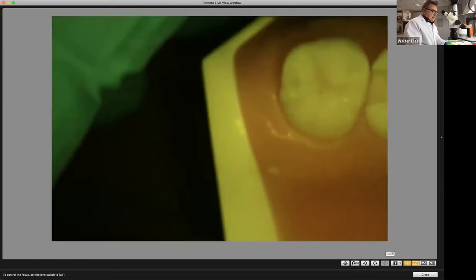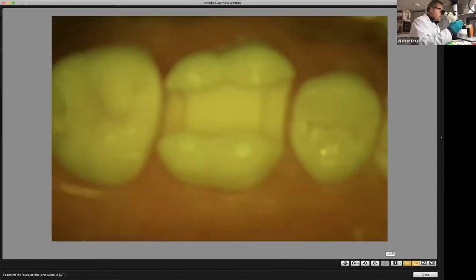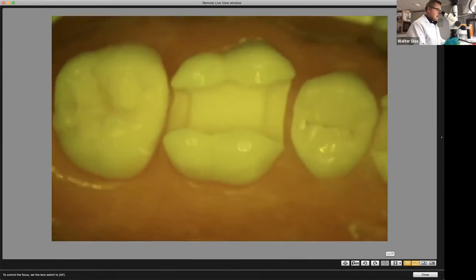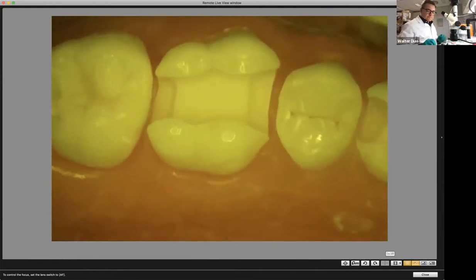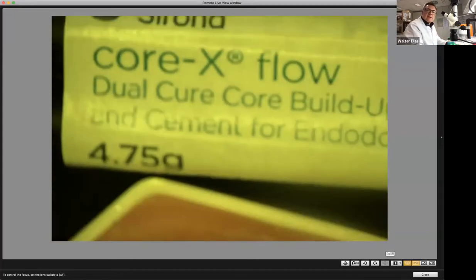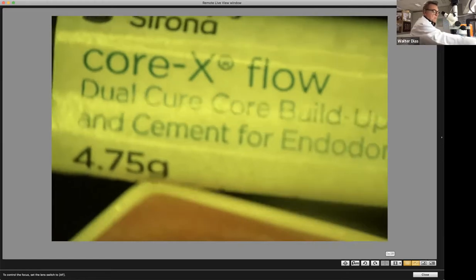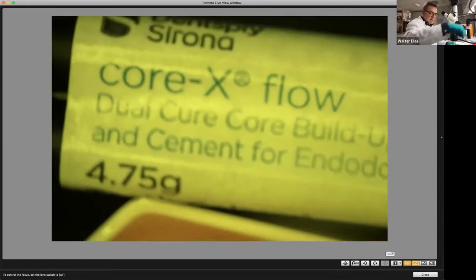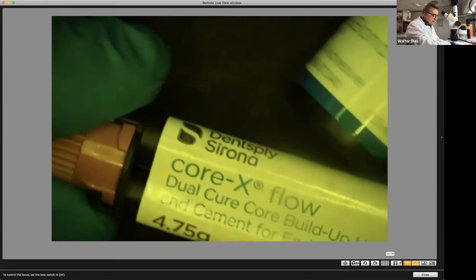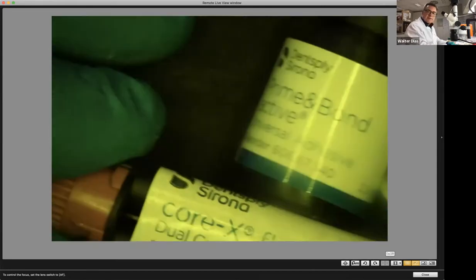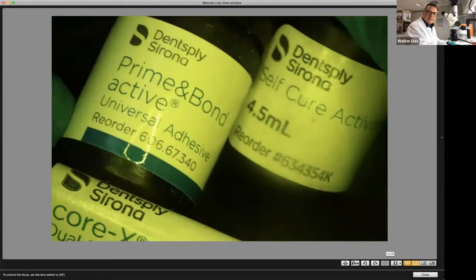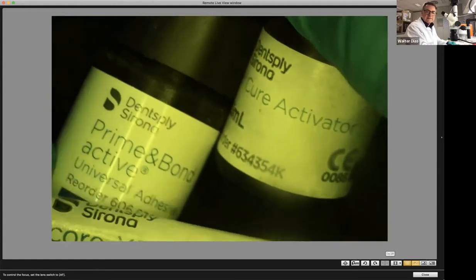So what we're going to do is use Core X Flow, which is a core buildup material that can double as a cement. So this is Core X Flow. And this Core X Flow can be used together with the adhesive and the activator. So I always recommend when you're doing core buildup that you use it in dual cure mode. So you have the self-cure activator, Prime&Bond active, and Core X Flow.